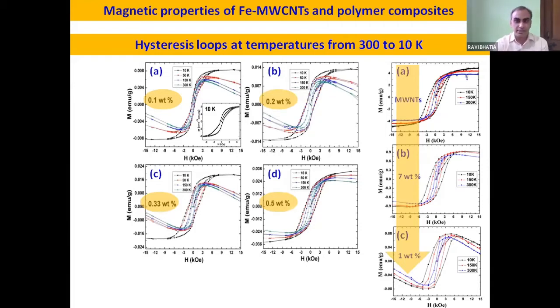Why? Because there was a very interesting feature that was observed, which probably cannot be seen in this graph, which needs to be tabulated. I will go to the table and explain. Before that, one can notice there are some changes at 0.1%, 0.2% and 0.3%. This is in agreement with the magnetic properties that if you have a bulk particle, the EMU, the magnetization values are higher, lower, even lower, and the least in the case of 0.1% sample.